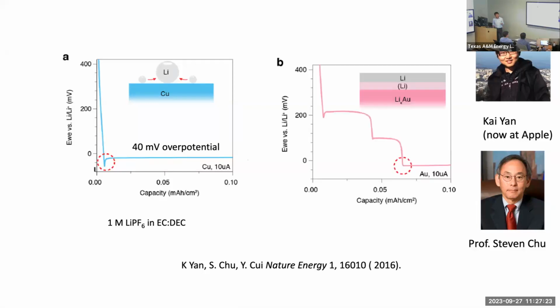But once you change the substrate, using gold as the substrate, it's different. Highlighted right here, this red circle, there's no voltage dip. Plating will just happen. So lithium metal plating onto gold has no overpotential for nucleation. Very different behavior. But certainly there's an upper voltage plateau right here. Lithium can go from the first alloy phase and then the second alloy phase.